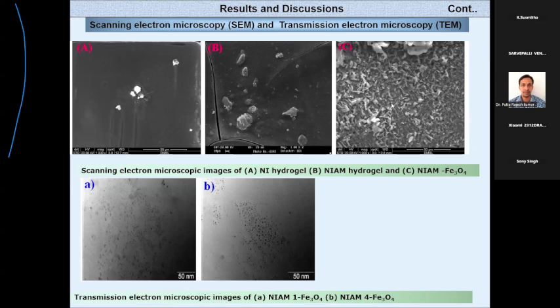By taking this sample, we did transmission electron microscopy images. What is the difference between scanning electron microscopy and transmission electron microscopy? Maybe some people are aware or may not. Transmission electron microscopy will give the particle size of the nanoparticles formed in your hydrogels. In the beginning of our presentation, I told you nanoparticles should always be uniformly distributed. Then only your application will benefit. If they form big clumps, you don't get much benefit. Here in the transmission electron microscopy, you are seeing all the particles uniformly distributed throughout the network. So this hydrogel will be very good for the application.